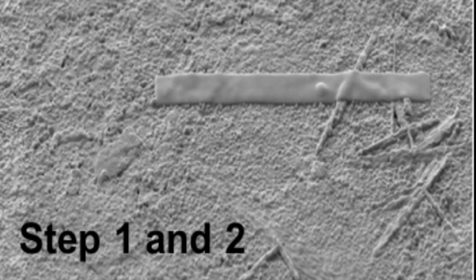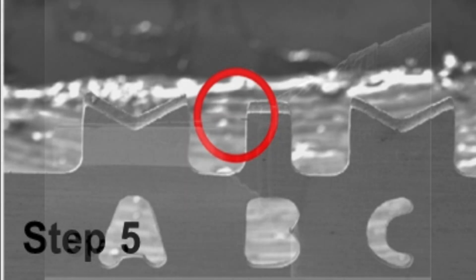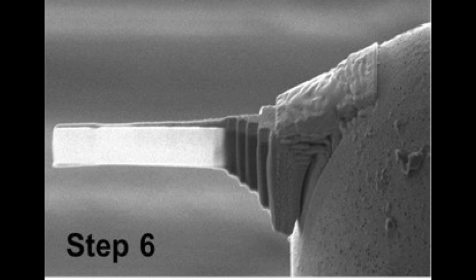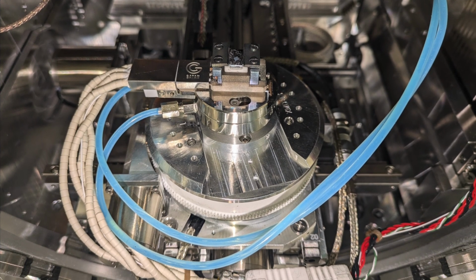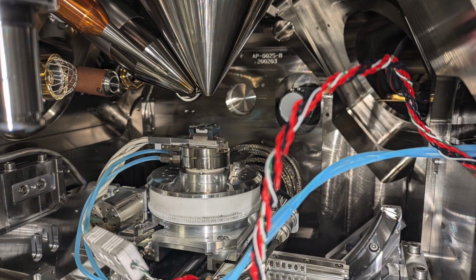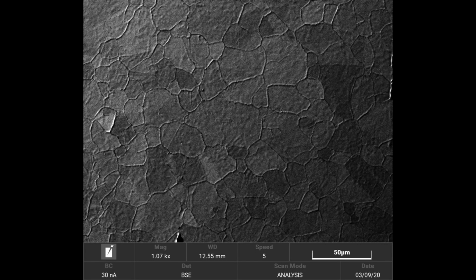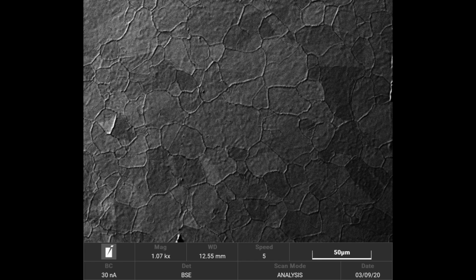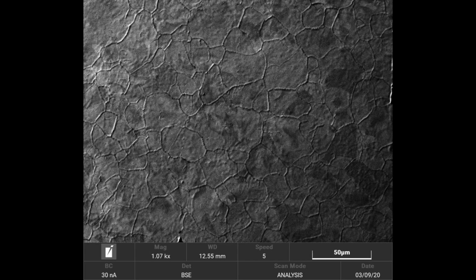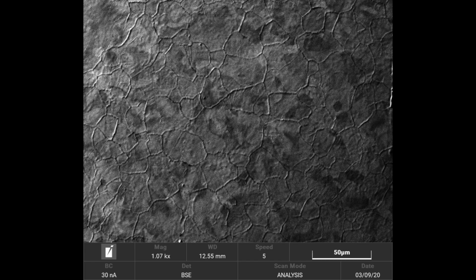For in situ TEM foil extractions, the SmartAct nanomanipulator offers 1 nanometer positioning resolution and is coupled with an electron flood gun for charge neutralization, ensuring precise milling of non-conductive samples. The Gatan Murano heating stage enables advanced in situ analysis, supporting experiments across a wide temperature range from room temperature up to 950 degrees Celsius, providing insights into material behavior under thermal stress.